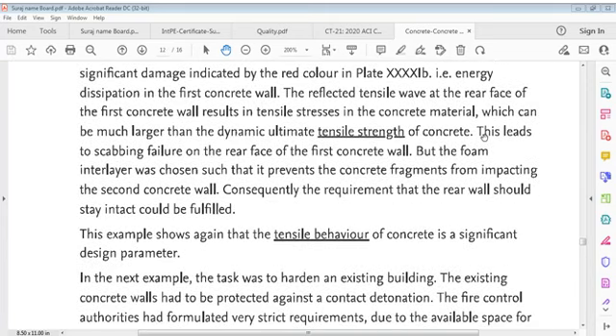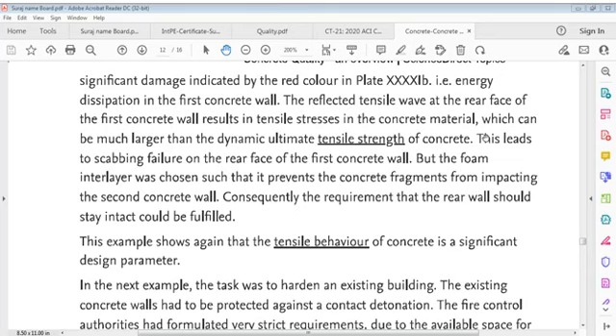We observe significant damage, indicated by red color, energy dissipation in the first concrete wall. The reflected tensile wave at the rear face of the first wall results in tensile stresses in the concrete material, which can be much larger than the dynamic ultimate tensile strength.